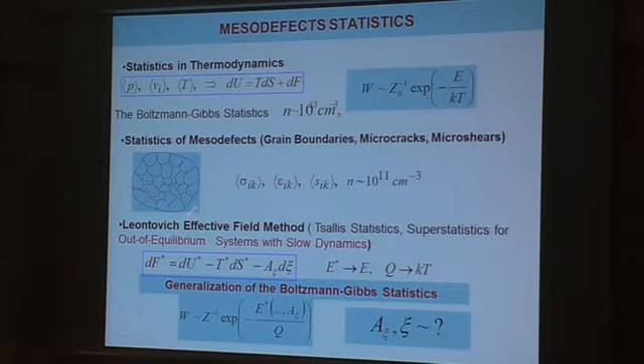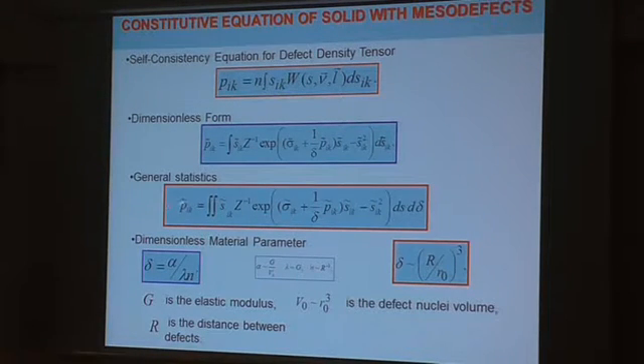A generalization of the statistical theory for out-of-equilibrium systems was developed, concerning generalization of Boltzmann statistics. And a procedure of averaging microscopic variables related to microcracks or microshears was realized, with the goal to obtain a constitutive law for the defect density tensor and its deformation induced by defects. And it was found that only a single parameter related to structure dramatically influences the evolution, and this parameter represents the ratio of the characteristic size of defects to the spacing between defects.